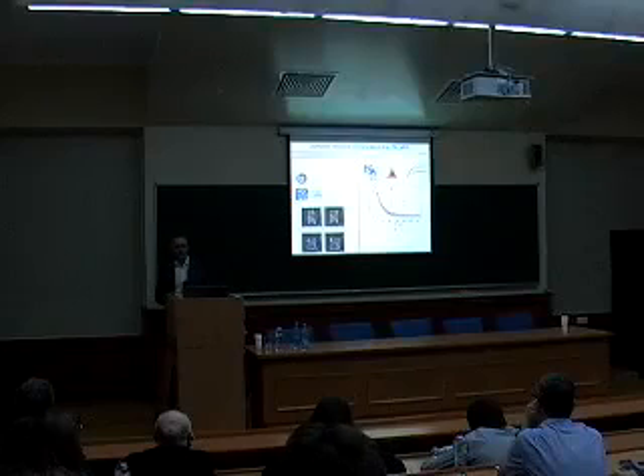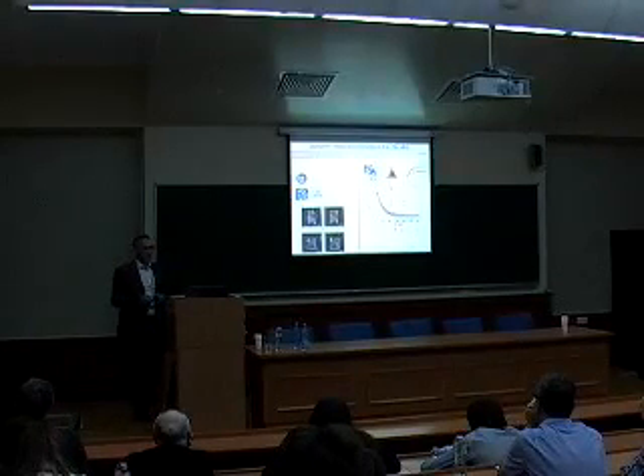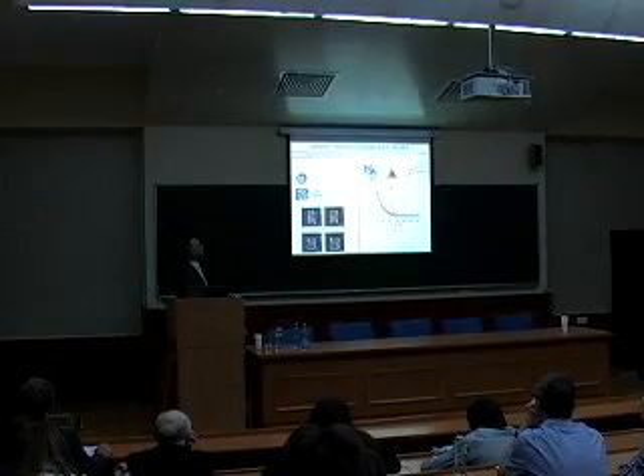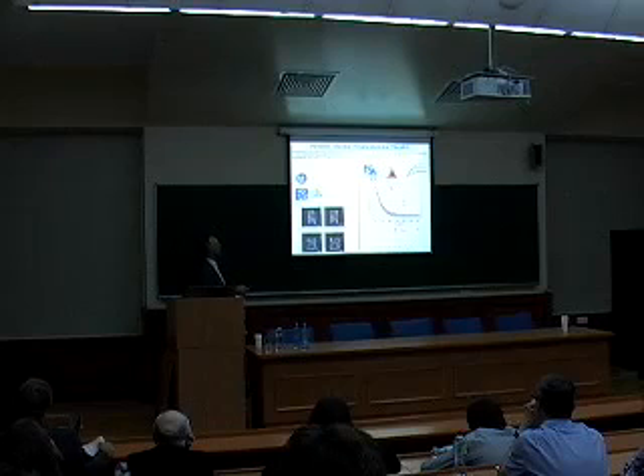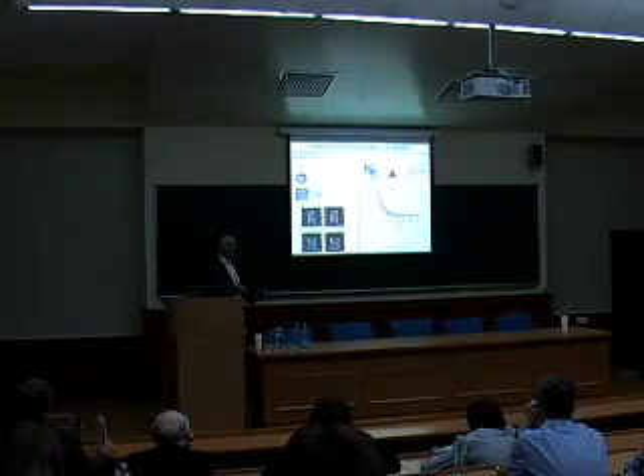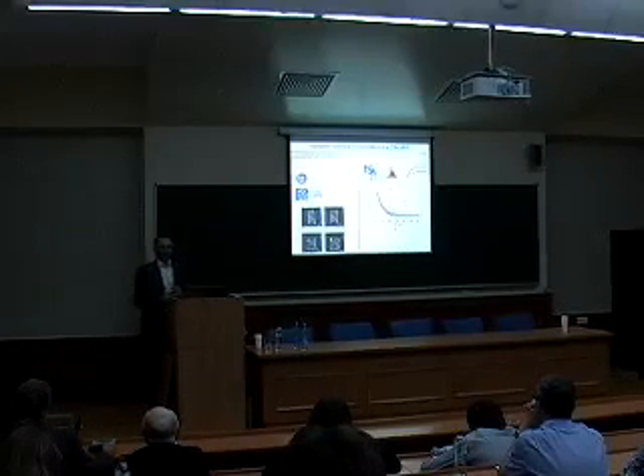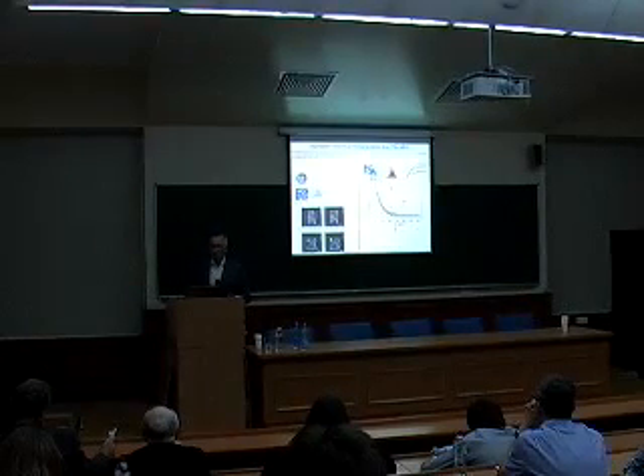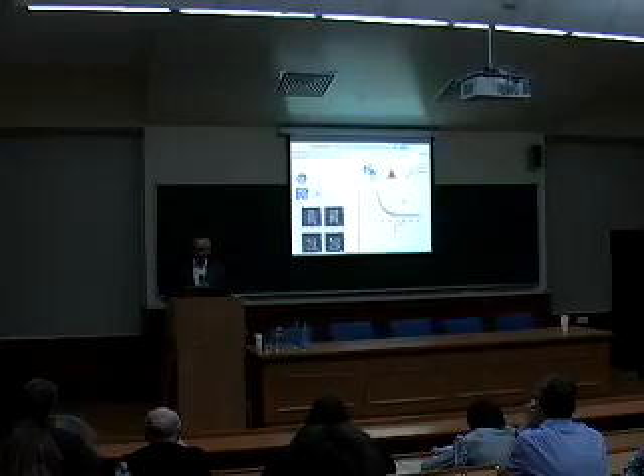And absolutely new results were obtained by a group from Switzerland. They succeeded in hyperpolarizing the smallest nanoparticles with size around 20 nanometers, and in this case, the time of depolarization, or relaxation of hyperpolarization, was a little bit less, around half an hour. They compared effects for coated and uncoated nanoparticles, which is very useful for further application. And I hope that such interesting results are very promising for further applications of silicon nanoparticles in MRI.